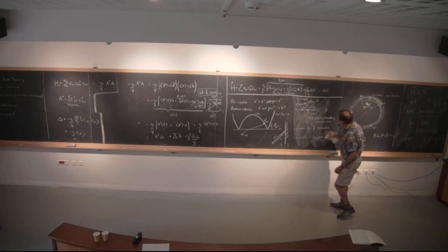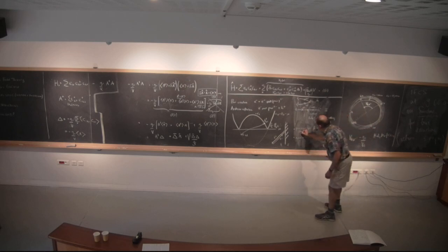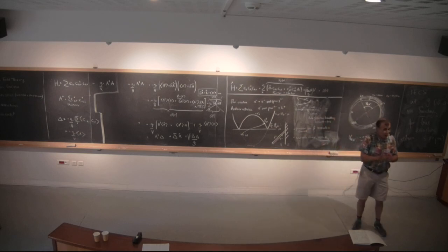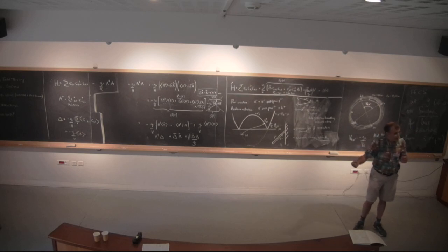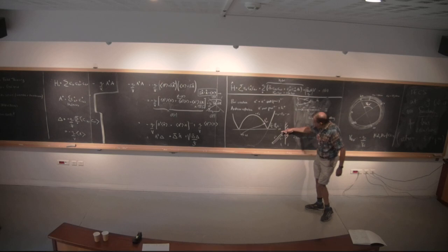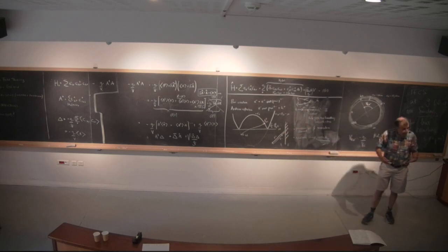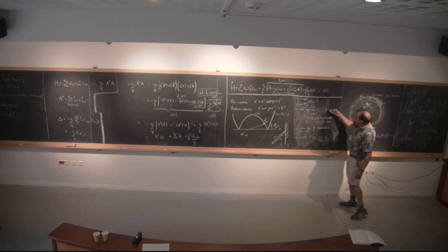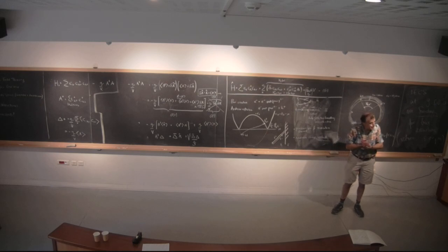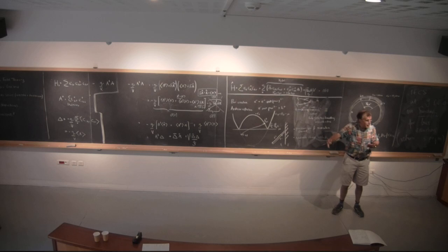And by the way, it also preserves current, believe it or not, because a hole traveling to the left actually has a current traveling to the right. Okay? So this kind of Andreev reflection, when it's observed, actually doubles the current that you send in. You get an enhancement of the current. So this process here is completely adiabatic. It's completely smooth. There's no jolting at all. It's completely phase coherent, but it reverses the velocity, okay?